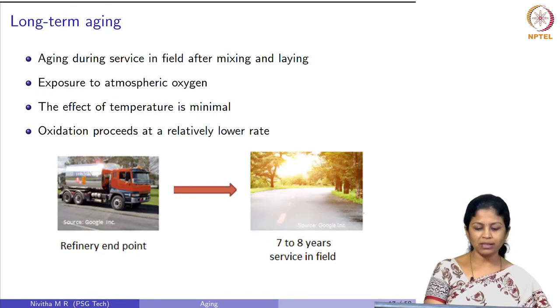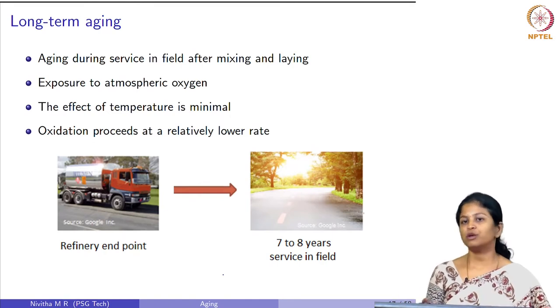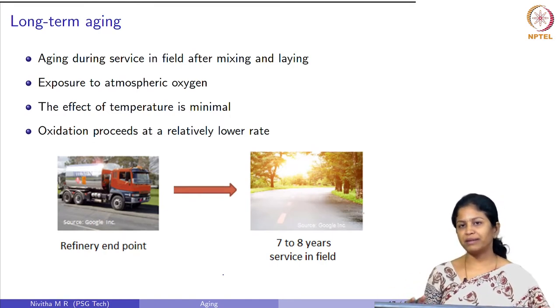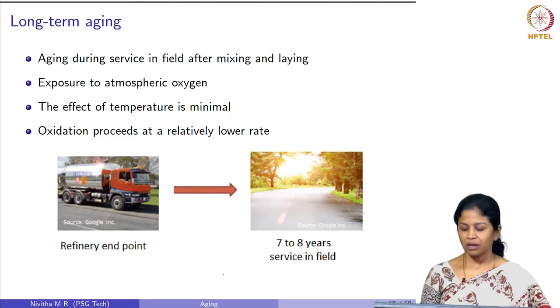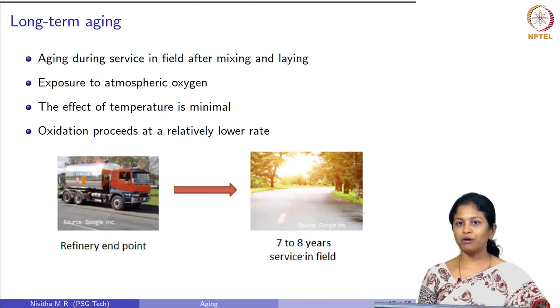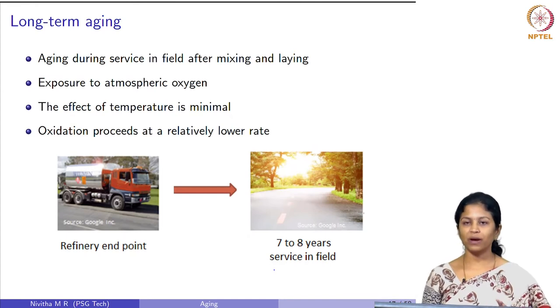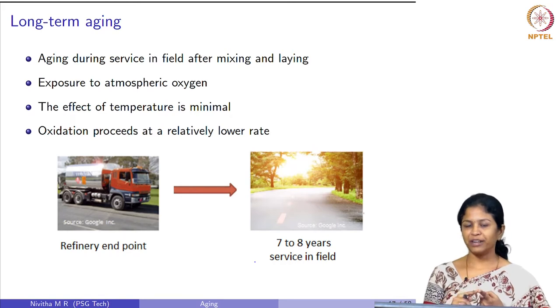In long-term aging, which is the aging during service in the field, we do not have high temperatures. In India, pavement temperatures may not exceed 70 degrees Celsius in most locations for most of the time. The material is still exposed to atmospheric oxygen, so oxidation proceeds at a relatively lower rate. The kinetics of oxidation are completely different in short-term and long-term aging because of the effect of temperature and the availability of oxygen.